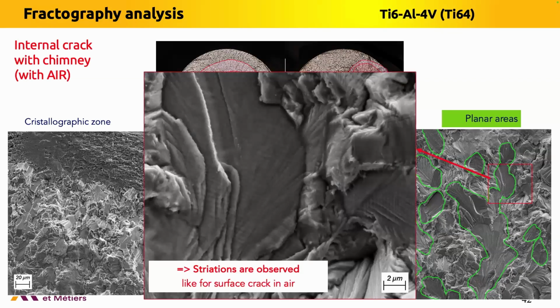If we zoom on these facets, we can see striations. Striations because of the presence of air, like for a surface crack in air. So it is typical in fatigue. We know that a surface crack in vacuum doesn't exhibit striations, but a surface crack in air exhibits striations. And here we observe that for an internal crack.